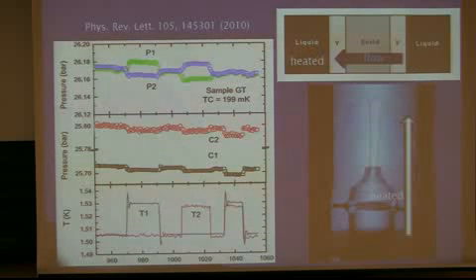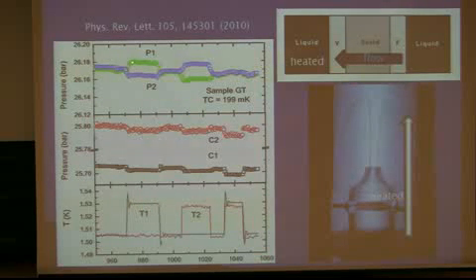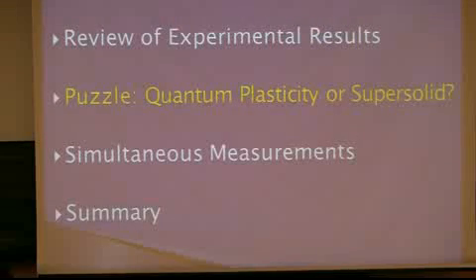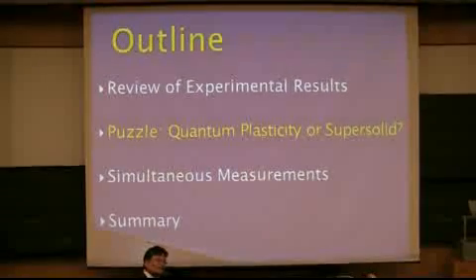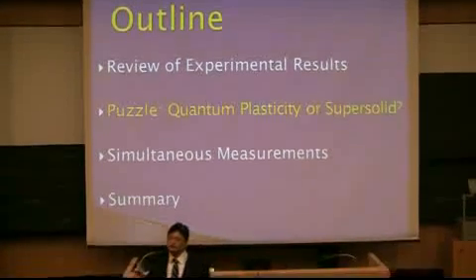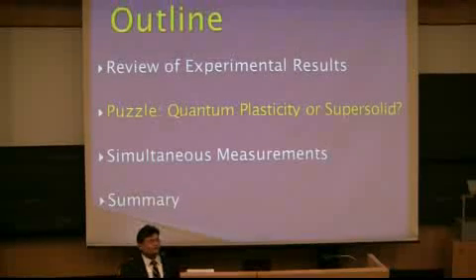Something like this. So here, what happened is, when you heat it, there is flow from the other chamber to this chamber. So you increase the temperature T1, so the pressure P1, or the pressure in chamber 1, increases, however, it decreases in chamber 2. So this means there is a flow from this chamber to the other chamber. And this must be superfluid. Okay? These are two very interesting experiments. So far, I tried to explain the existence of non-classical rotational inertia and other supporting evidence for this supersolidity.